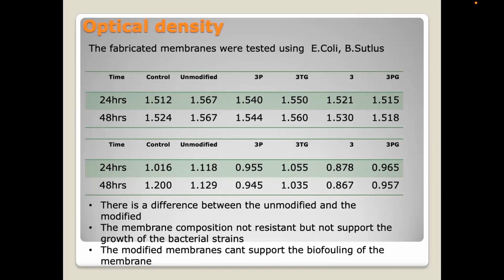Also, we tested the biofouling by the optical density. From this table, it's clear that there is a little bit of difference between the unmodified and the modified. The membrane composition is not resistant but does not support growth of the bacterial strain. The modified membranes cannot support the biofouling of the membrane. From both experiments, we conclude that our membrane cannot support the biofouling, especially with surface treatment.